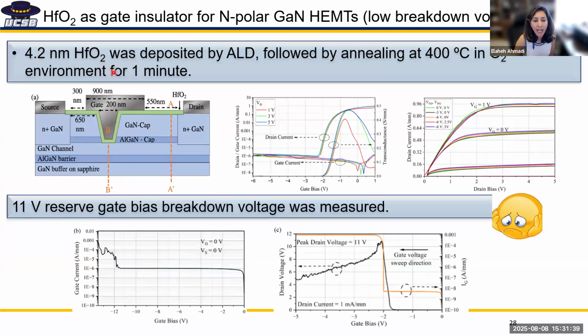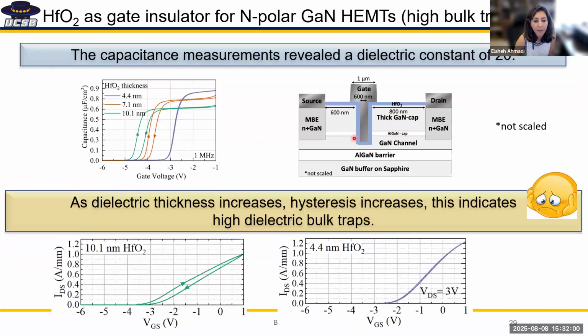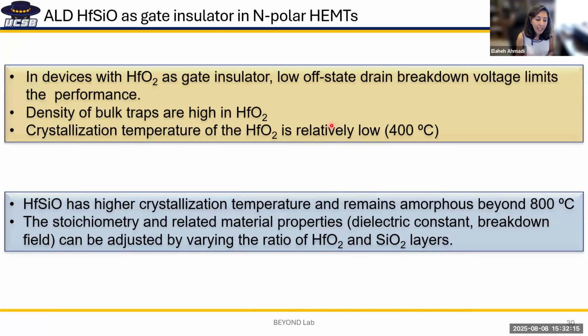So initially we started with hafnium oxide. The pulsed IV measurements were good, the DC characteristics were good, but then we had low breakdown voltage on these devices. And when we tried to increase the hafnium oxide thickness to see if we can increase the breakdown, what we saw is that we got a larger hysteresis with the thicker hafnium oxide, and so this was not acceptable.